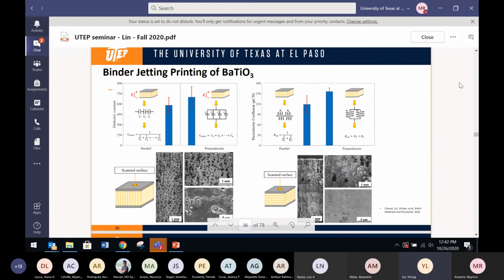Okay, so what we're showing here is we measured its dielectric and piezoelectric property. In other words, to measure how good of a sensor it is, right? So what we're showing here is, by the way, you electrode them differently, either on top and bottom or left and right after you printed them, and we can control the dielectric and the piezoelectric coupling coefficient. In other words, we can control the way you use it as a sensor, either sensitive to pressure or sensitive to temperature. Next slide.